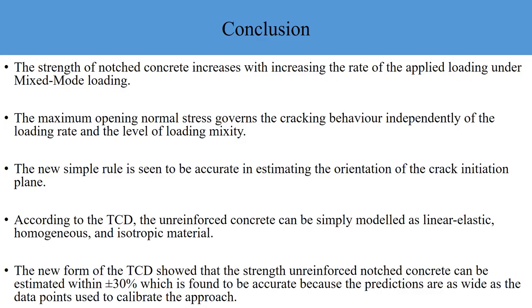The outcomes of this research can be summarized as follows: the strength of notched concrete increases with increasing loading rate under mixed mode loading; the maximum opening normal stress governs cracking behavior independently of loading rate and level of loading mixity; the new simple rule is accurate in estimating the orientation of the crack initiation plane; and unreinforced concrete can be modeled as linear elastic, homogeneous, and isotropic. The new TCD extension estimates the strength of unreinforced notched concrete within ±30%, which is considered accurate as predictions are as wide as the calibration data. Thank you for listening.